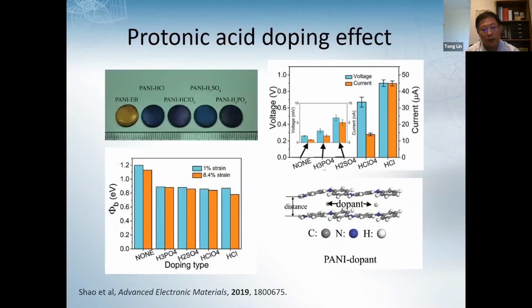Using polyaniline, we can also understand how the dopant influences the energy conversion, because polyaniline can be doped, de-doped and redoped by different acid dopants. So we use the same batch of polyaniline and de-dope it, and after that we redope the de-doped material with different acids and prepare the discs. The discs like this contain different acid dopants. We found that the dopant indeed influences the energy conversion ability. The one with the smallest size leads to larger energy conversion ability. The reason is that a smaller dopant gives sufficient dopant levels, and it also reduces the barrier height in the compression state.